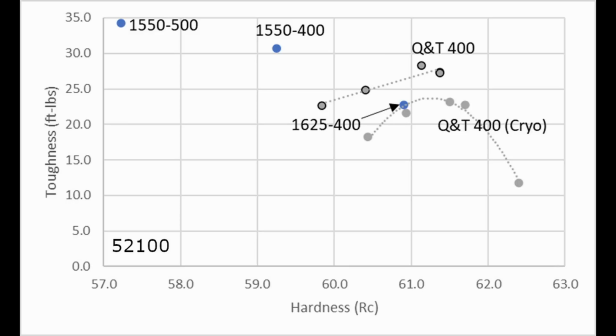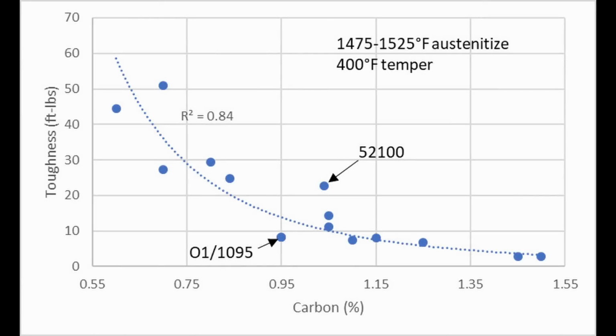Now, why would the Austempering not have too much more toughness than the quench and temper? There's a few reasons. One is that at 1625, probably there's a little bit of grain growth with the 52100, which will reduce the toughness some. Another thing is that 52100 does not really have the same level of issue with plate martensite as steels like 01 and 1095. Even though 52100 is also a 1% carbon steel, the 1.5% chromium addition means that you have less carbon in solution after heat treatment, unless you austenitize pretty high. And so it usually has 0.6% carbon in solution, or maybe even a little bit less. And so the improvement in toughness is less in 52100 than the two other steels I'm going to show in just a minute.